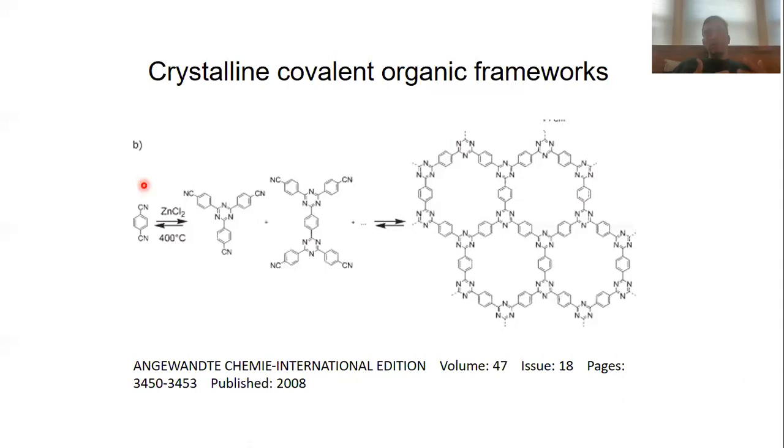Okay, so this is generally still an issue with covalent organic frameworks. The crystallization of these frameworks is often not very predictable. And even if you make just a small variation to your reactants, and you can easily draw an analogous crystalline framework on the sheet of paper, not necessarily that crystalline organic framework will form.